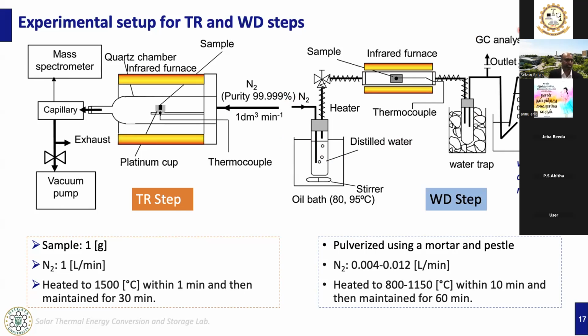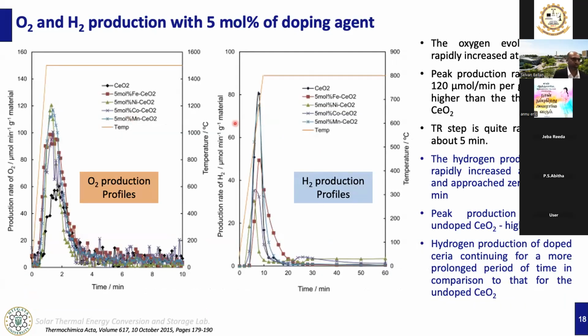And here you can see the oxygen and hydrogen production rate with 5 mole percentage of doping agent. For example, manganese, copper, nickel, and iron doped cerium oxides, all samples with 5 mole percentage of doping. So as you can see, this is the oxygen production rate, and this orange line shows the temperature. As soon as it reaches or goes above 1,000 degrees Celsius, the production rate reaches the peak level, around 90 to 120 micromole per minute. So this step is very quick and rapid. Within 5 minutes, the thermal reduction step is done.